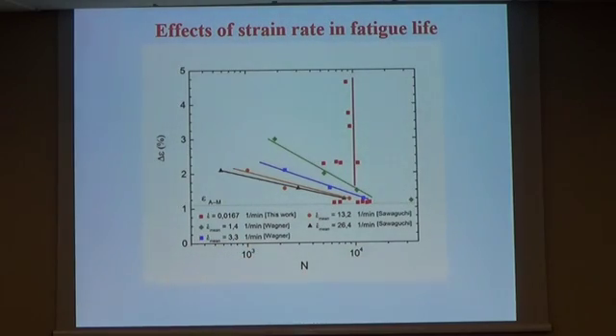Just two more things. Remember, the effective strain rate is quite important. Here are our results, and here are some equivalent strain rates from results in the literature by Wagner and Sawaguchi. This one is two orders of magnitude above our test. But it's clear there is an effect of the strain rate due to thermal effects.